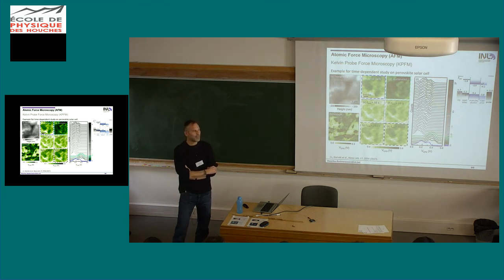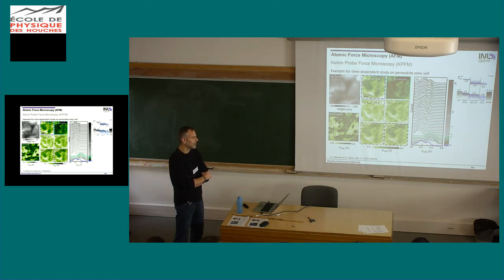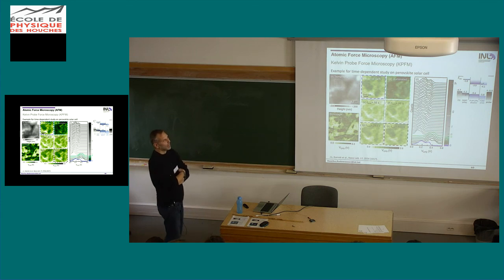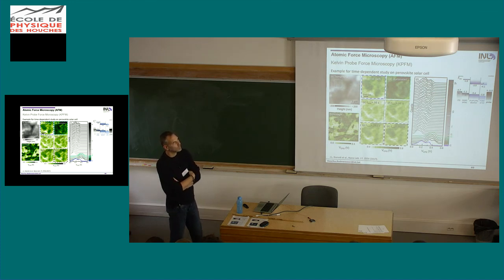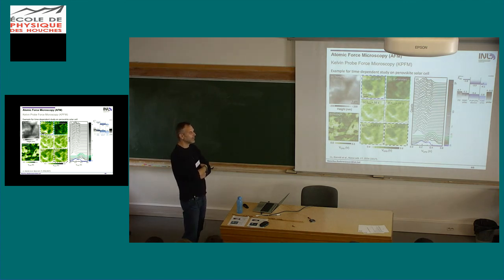Maybe one short question from me. You showed in one of the first slides a method for measuring doping using these MOS structures. I saw that your signal was kind of saturating at around 10 to the 18 per cubic centimeter. Is this something specific for that particular material measurement, or are there some problems in measuring higher doping levels? I don't know. No, I wouldn't know. Maybe this was just the reference sample they were fabricating. I think this was a stacked silicon doping profile for these calibrations. I don't know.